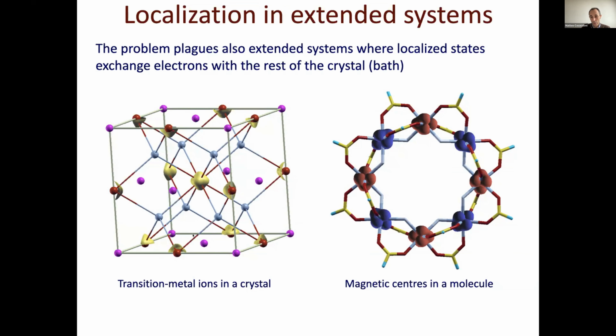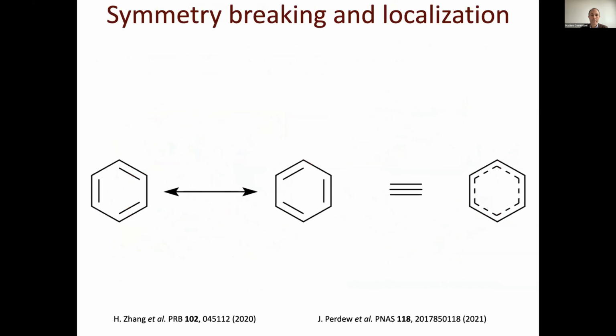And that can lead to significant error, like I showed before, also for the magnetic properties. For example, underestimation of localized magnetic moments, or overestimation of magnetic interaction between sites are the typical consequence of this over-delocalization of d or f electrons over the unit cell.